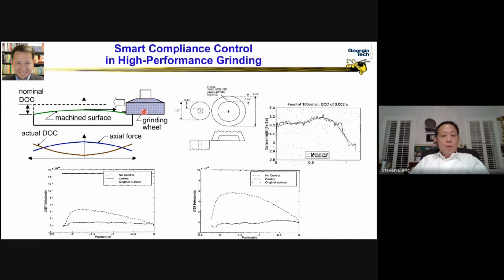So most of us have this experience, if you grind a part left and right, and then left and right again several times, so the two shoulders will get ground off pretty fast, and the center portion will be bulging out. That is pretty much because of the flexibility of the machine tool structure itself. So what we have done is to close the loop by measuring the instantaneous deflection of the workpiece and the grinding force, in coupling with the actuation and feedback control of the quill height of the grinding wheel, so that when the wheel gets to the center portion of the workpiece, it is pressed downward a little bit more to compensate for that loss of depth of grind.